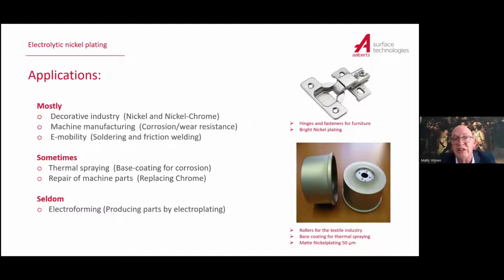Another place where you see it is machine manufacturing, for corrosion and wear resistance. With corrosion, I mean when the layer is closed enough, thick enough, that there are no pores. And for wear resistance, it's not the hardness that is demanded, so not the abrasive wear resistance, but more the adhesive wear resistance, where the toughness of a layer is demanded.